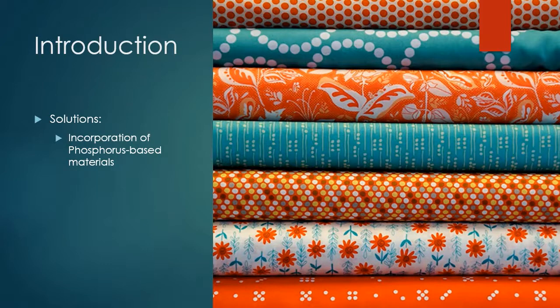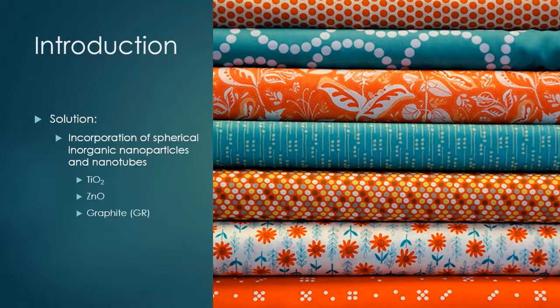So one solution to address this problem is the incorporation of phosphorus-based material to increase the flame retardancy of the textile fiber. However, the application of this also causes some problems, and one problem is the loss of mechanical properties. With the use of the phosphorus nitrogen based material, we were able to increase the flame retardancy. However, we lose the mechanical properties. That is why a solution for this could be the incorporation of spherical inorganic nanoparticles and nanotubes.